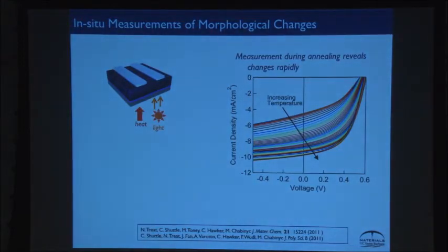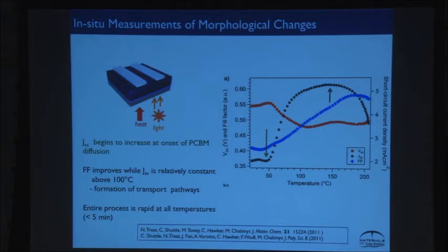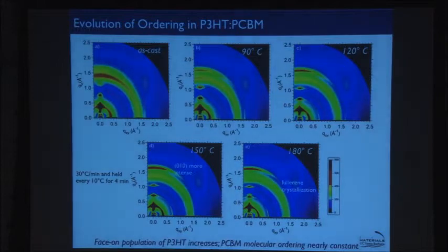We could also see this in other ways. So we actually did this experiment, which again we were surprised no one had done. What we do is we measure the solar cell in situ while we heat it. And we actually see at temperatures right when we know the fullerene diffusion goes in, that's exactly when the short circuit current, all the improvement in the solar cell performance starts to happen. It actually shoots up very strongly, just right around when the fullerene diffuses. And so this was telling us that this fullerene diffusion is one of the most important processes in getting these solar cells to work.